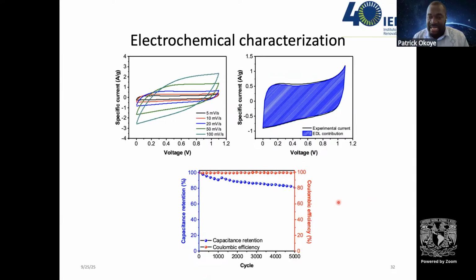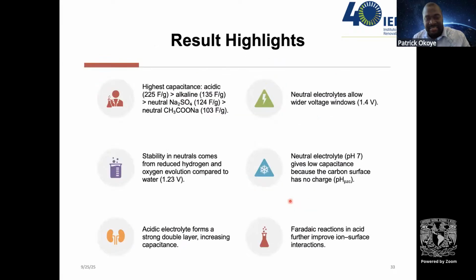And this material could be used in terms of its charge retention and capacity retention for over 5,000 cycles of charge discharge. You could see the capacity retention only decayed a little bit to about 80%, and the coulombic efficiency of our material is 100% and was stable throughout. So this shows that this material is very fascinating in itself because we were able to have up to 225 farads per gram, which is one of the best performing materials for carbon electrodes.